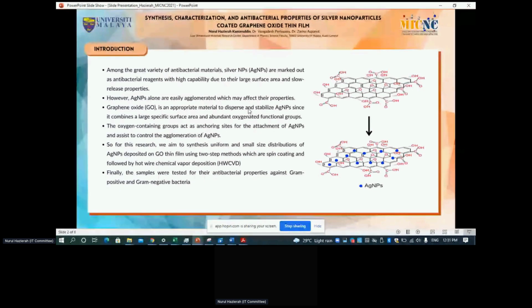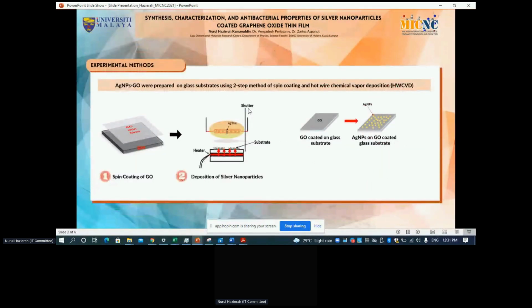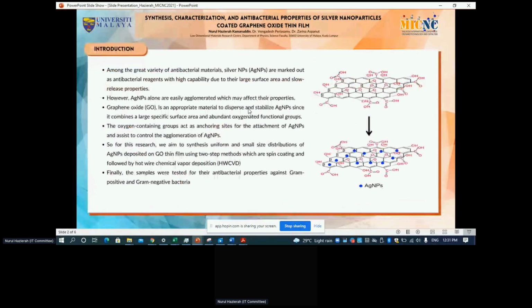The oxygen-containing group acts as an anchoring site for the attachment of silver nanoparticles and assists to control the agglomeration of silver nanoparticles. So for this research, we aim to synthesize a uniform and small size distribution of silver nanoparticles deposited on graphene oxide thin film using a two-step method, which are spin coating followed by hot wire chemical vapor deposition. And finally, the samples were tested for their antibacterial properties against gram-positive and gram-negative bacteria.